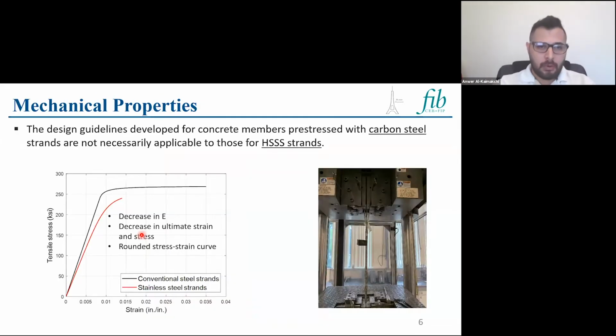Starting with the mechanical properties, we can see the stress strain curve of the stainless steel strands, the red one, is fundamentally different than that for the carbon steel strand. It has a lower elastic modulus, and a lower ultimate stress and strain. And we can see that it has a rounded stress strain curve up to failure. So there is no plateau, there is no defined yield, unlike the carbon steel strands.